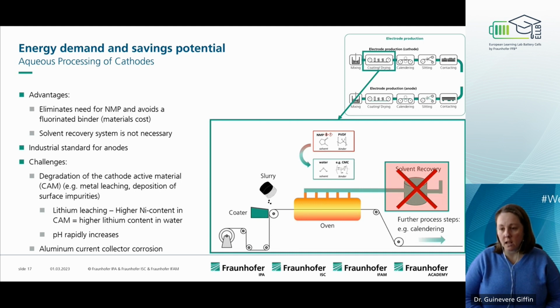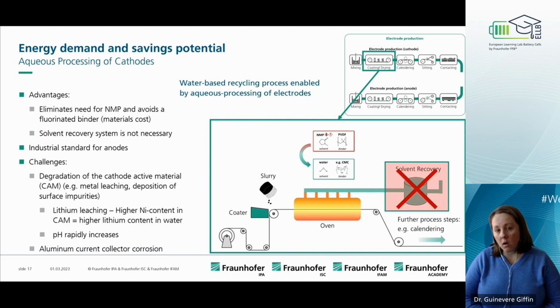However, on the cathode side, there are specific challenges associated with the active material itself, which make this challenging. So, for example, degradation of the cathode active material can occur. So things like the leaching of metals and the subsequent deposition of surface impurities. In particular, lithium leaching is an issue, and this is generally worse when you have a higher nickel content in the active material itself. This results in a rapid increase of the pH and current collector corrosion. However, here you have to look at advantages and disadvantages. And one aspect that may actually help in realizing aqueous processing is that this could also enable water-based recycling processes. So here you might see the recycling aspect influencing the production processes in the future through what's called design for recycling.